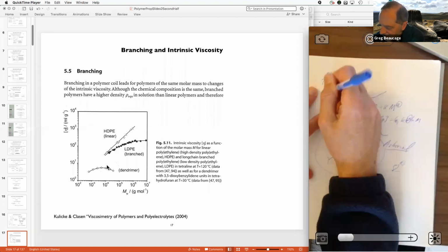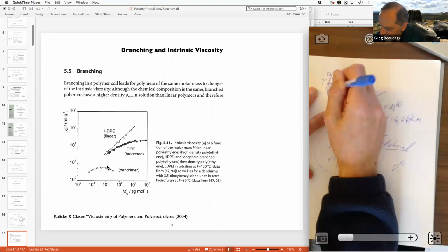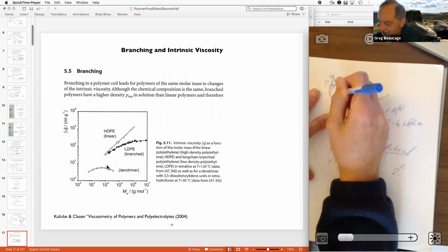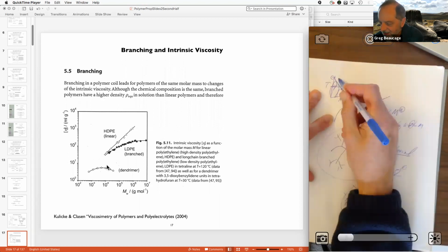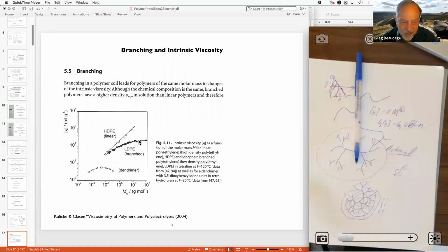So as you increase molecular weight, say you're at a temperature here, the low molecular weight one would be soluble, and the high molecular weight is insoluble. So there's also a solubility issue. As you go across molecular weight, the solubility drops, and it could become insoluble and precipitate out. There's a lot of things that could happen. They're trying to get rid of that because they put the same material here that shows that it didn't precipitate out. But who knows what happens when it branches, right?